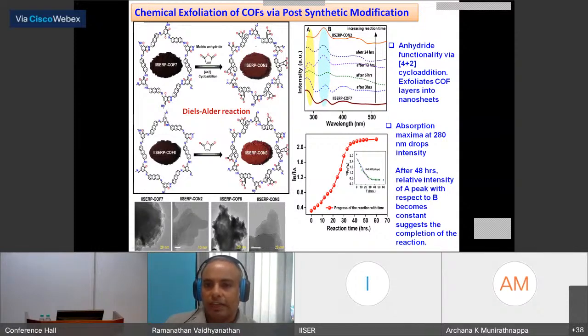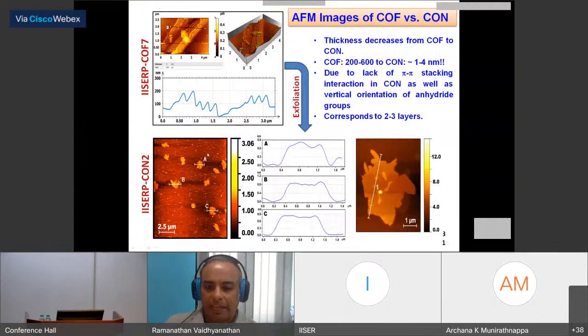So if I call this other groups' intensity B and the intensity of the anthracene A, and then I plot it as a function of time, you can see that the reaction is complete in 48 hours. That means all the anthracene units have been converted into maleic anhydride adduct. So I have completed my organic reaction. So it is a very trackable reaction. And you can also see that the TEM clearly shows the thick COF has been exfoliated into very thin layers. How thin? That can be seen from the AFM studies.